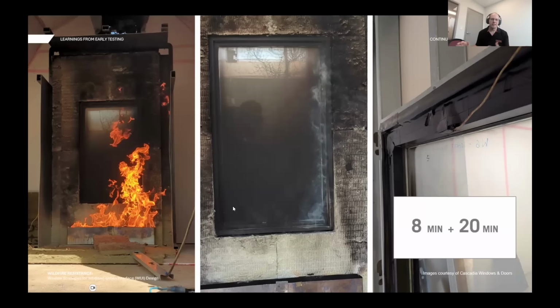We actually wanted to see what would happen to the frames if we subjected them to longer than the 8-minute test. So for the sample where we had the fireproof glass as the IGU, we did the 8-minute test. We took a 5-minute observation period to make sure it was out and just to take some photos. And then we turned the test back on for over 20 minutes. And we just sat there getting bored because as it turns out, it takes about 8 or 9 minutes for the outer resin to combust. And then once it's combusted and you've got just dirty glass on the outer surface, not much happens after that. I guess eventually something would, but 20 minutes later, the frame was pretty much exactly the same visually, and when we cut it, as it was after just the 8-minute test.